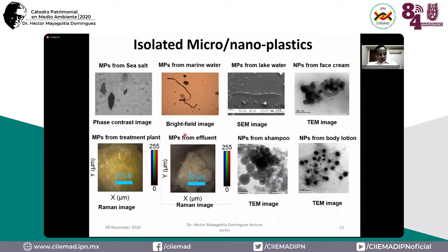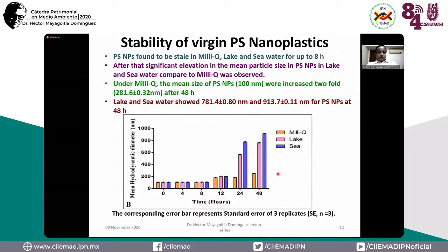The problem comes when we use a plastic for a one-time purpose. These plastics have now been proven to cause environmental effects as well as human effects. So we did a small study in a lake water ecosystem, and also compared it with the seawater system. This was a small microcosm study where we took a polystyrene nanoparticle, virgin polystyrene, and we could see that over a period of time, the size of the particles started to increase.